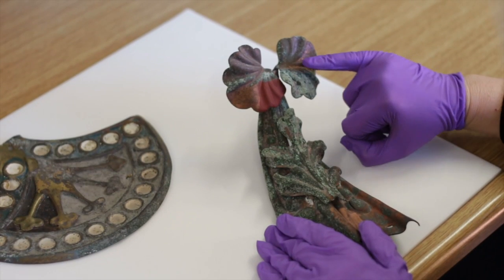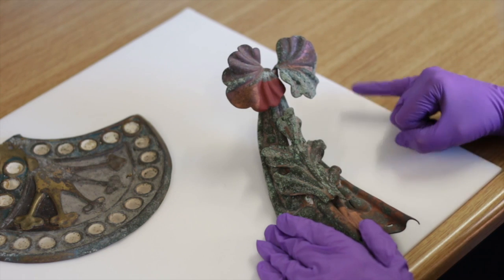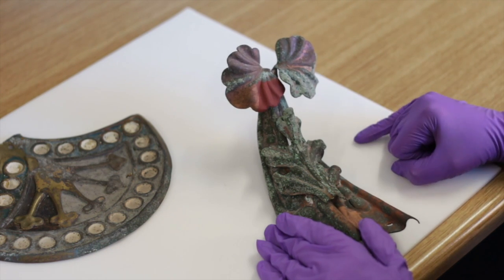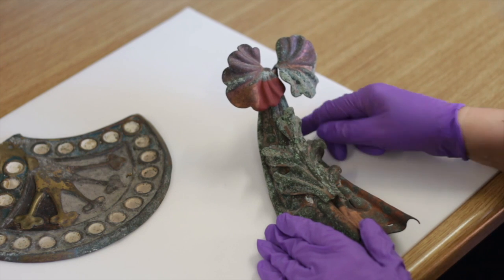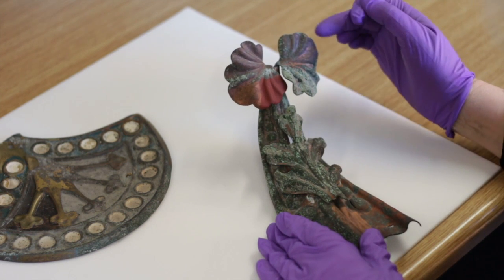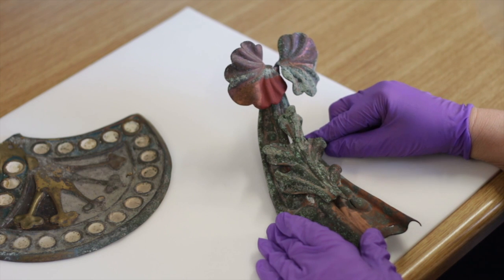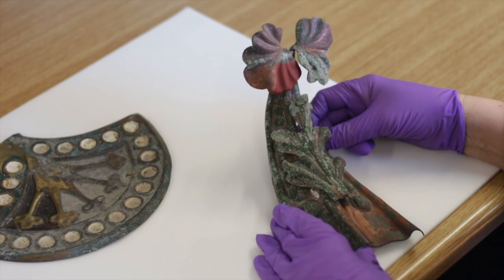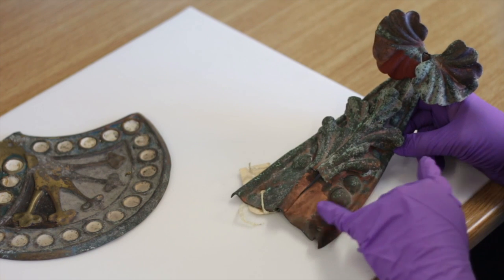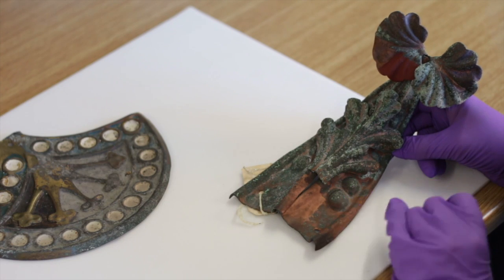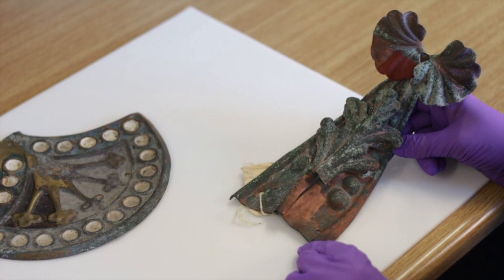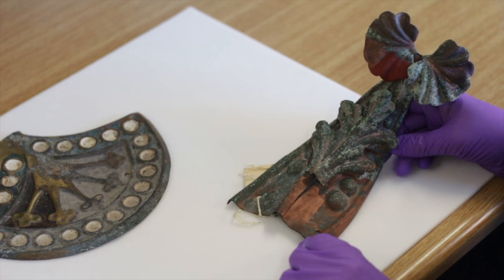And what it did also produce was this slightly purplish hue, like an interference layer on the copper, which has still remained after quite a number of years. It would be possible to remove this purplish hue, but it would mean you still have to use some sort of abrasive method to do so. What was found to be most effective was this area here. Given that the corrosion is irregular, using a micro-air-abrasive device with aluminium oxide was trialled, and that effectively and gently removes the corrosion, reveals the underlying metal, renders it stable, and then following on from that,